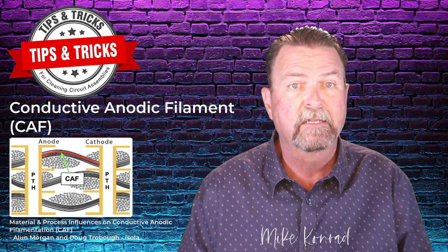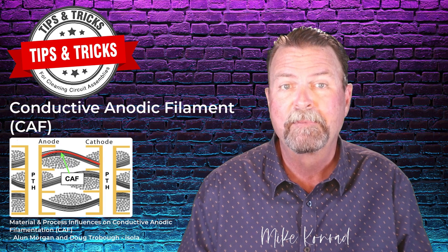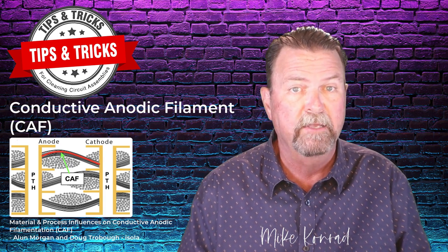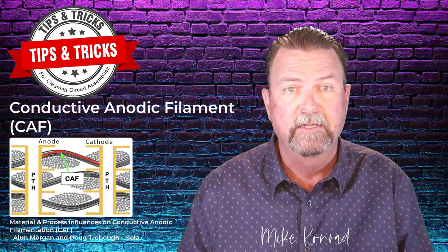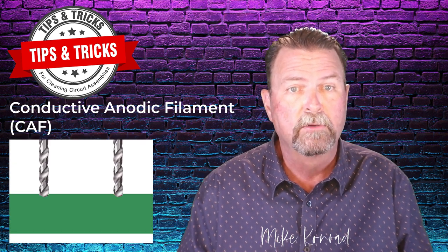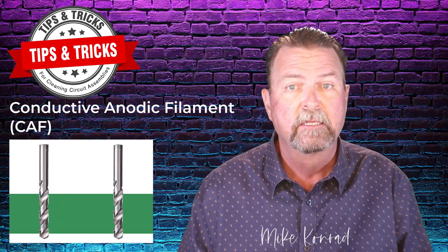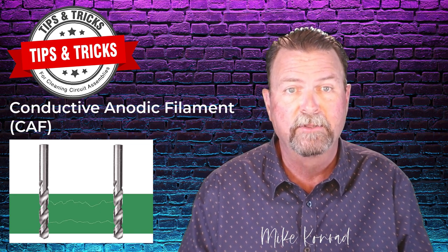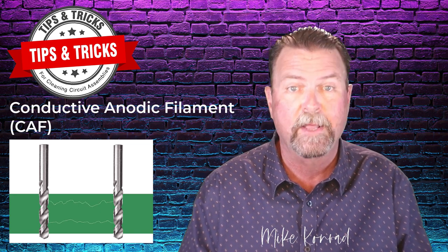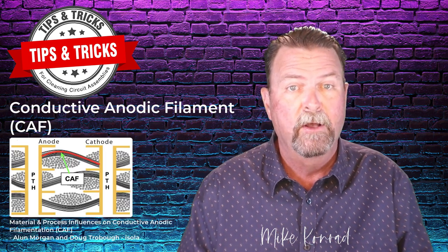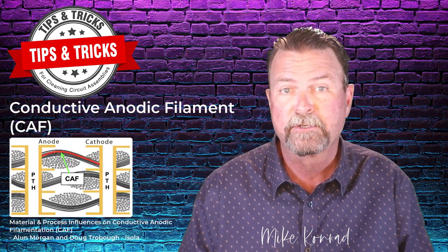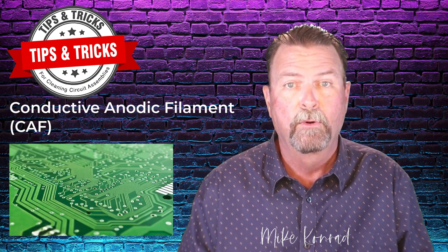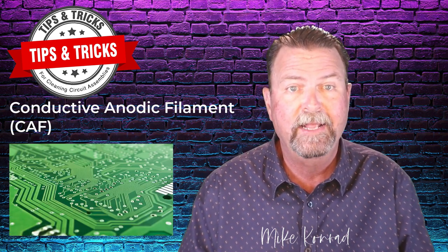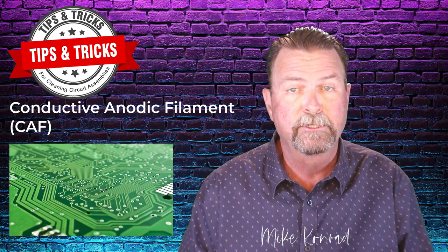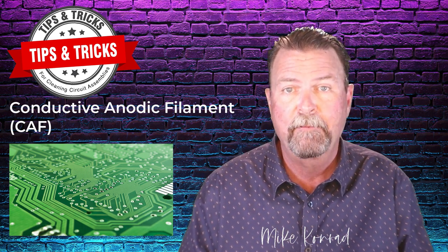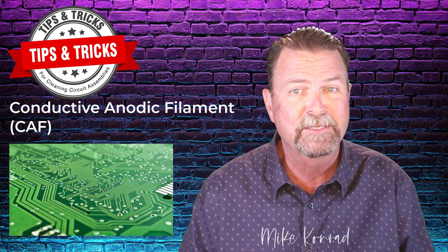Pathways may be created when the glass resin in the board material becomes separated, commonly referred to as dry weave. Pathways may also be created during the drilling process. As through holes and vias are drilled into the board, dull drill bits or excessive pressure on the drill bits may cause damage to the laminate, creating pathways. Damage to the laminate may also occur as a result of multiple thermal excursions. After the drilling process, the through holes and vias are plated using a conductive plating solution. The conductive plating solution can leach into the gaps in the laminate material, providing one of the three necessary pillars of ECM.